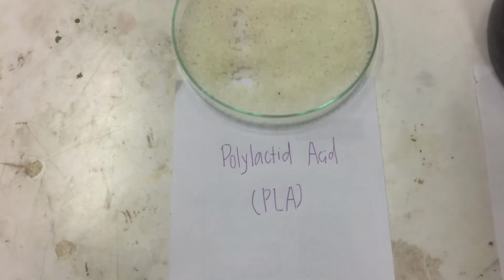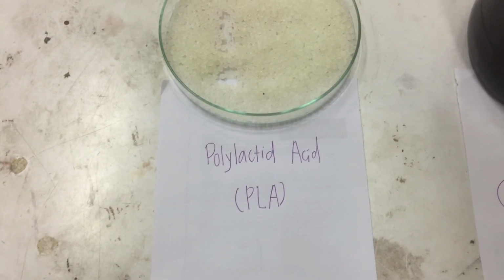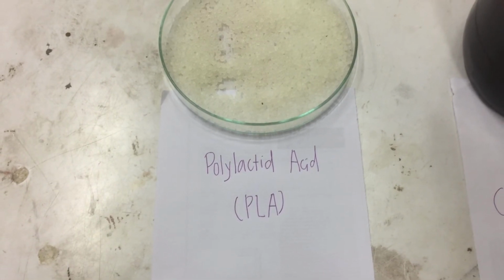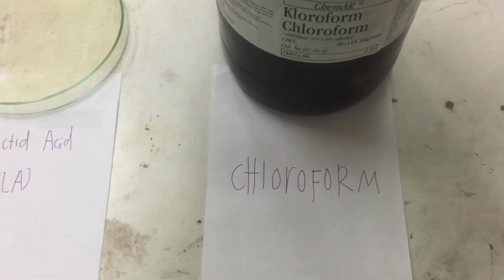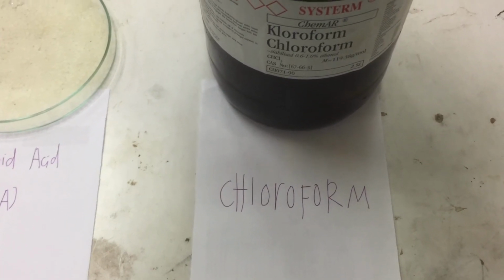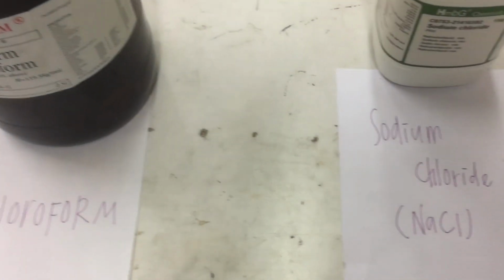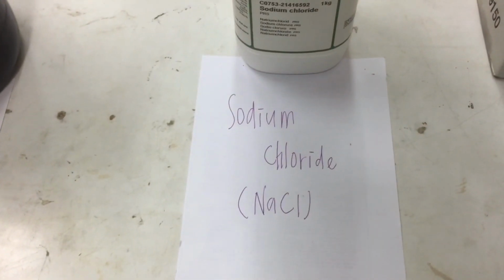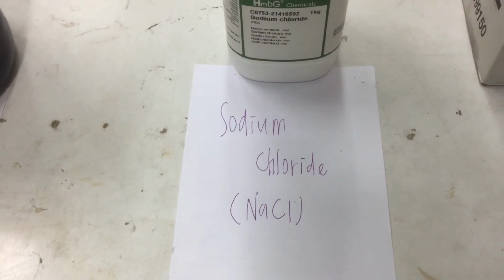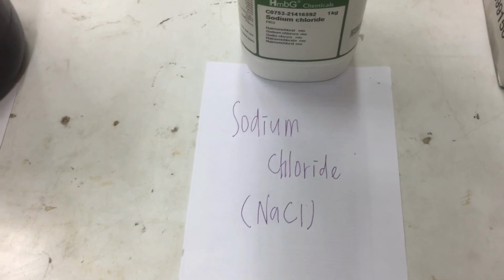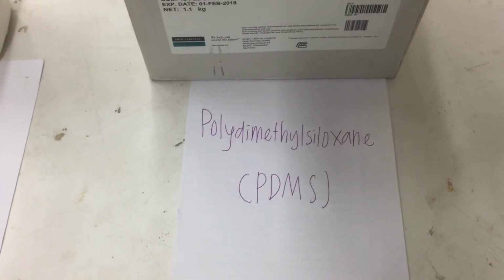We are going to discover our raw material and our highlight procedure. For the first material, we use polylactic acid PLA in pellet form. As a solvent, we use chloroform to dissolve the polylactic acid. To produce porous PLA, we use sodium chloride NaCl as porogen agent. To enhance our porous PLA, we use polydimethylsiloxane PDMS.